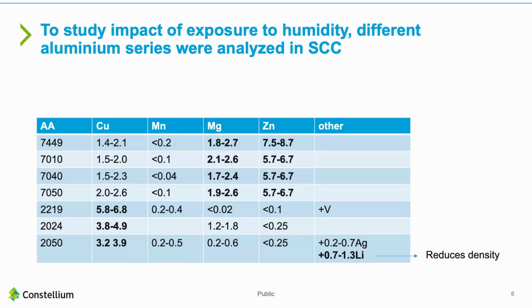We have conducted a study on different aluminium alloys. So first, 7000 series. For that kind of aluminium, we have principally as the main addition elements zinc and magnesium that form the hardening phase. We have also considered 2219, which is an incumbent alloy for space launchers. It has a high level of copper. In fact, it's above the solubility limit, which could be improved.